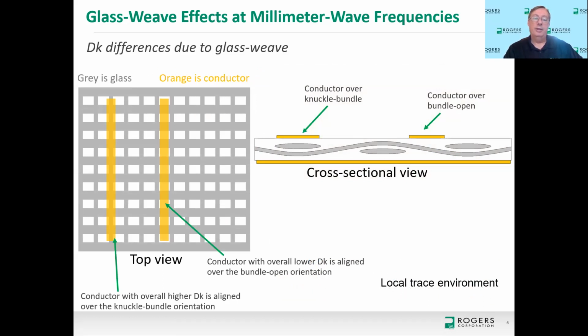And that's because the conductor on the left is aligned to the glass weave pattern in such a way that it's over two layers of glass in some cases and one layer of glass in another. So it's really over a knuckle bundle orientation, as I would call it. So from the bottom of this top view picture going up, you would have the conductor, it's aligned over a bundle of glass, the knuckle, bundle, knuckle, bundle, knuckle, bundle. And the overall effect for that signal conductor would be a higher effective dielectric constant than the neighboring conductor to the right that is aligned to the glass weave pattern over an area of an open area with no glass, and then an area of bundle, one layer of glass, and open bundle. So I call that the bundle open orientation.